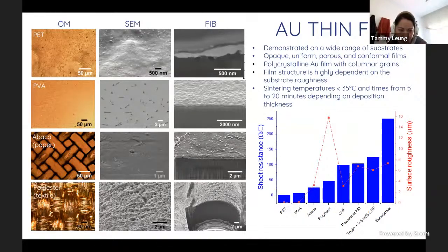And specifically, when looking at the different substrates, we were able to determine the relationship between the sheet resistance and the surface roughness, which roughly follows a linear, or directly proportional, relationship. That is, the sheet resistance increases as the surface roughness increases. Polyester here was sort of an outlier. However, polyester fabric itself is actually a polymer, so the ink stays on the surface and is available to be converted, therefore explaining the lower sheet resistance that you see here.